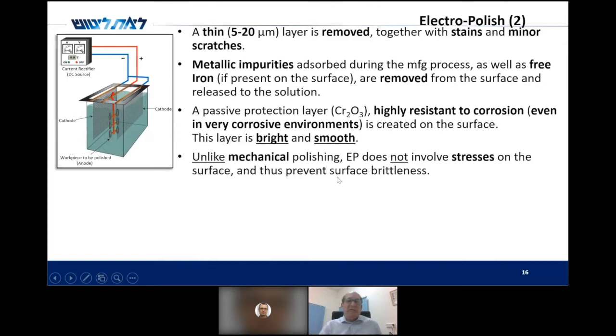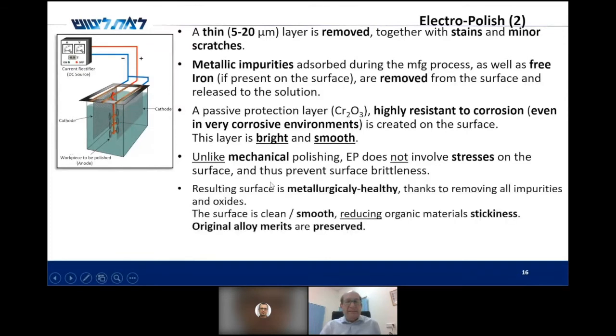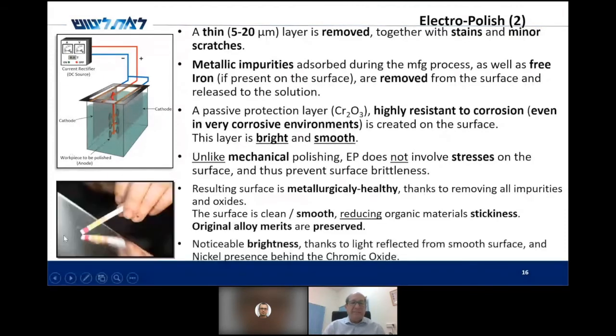Unlike mechanical polishing, electro-polish does not involve stresses or all sorts of forces that create stress in the material, and thus prevents surface brittleness, which is a good merit. And the resulting surface is very healthy in terms of metallurgy, because all the impurities and oxides are removed. It is clean, smooth. No organic materials can stick to it, or can less stick to it. And all the original alloy merits are preserved. And as you can see here in this picture, there is noticeable brightness thanks to the light reflected from the smooth surface and the nickel content below the chromic oxide layer.